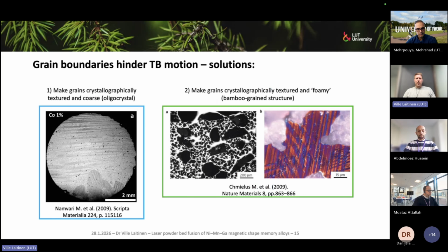Now, how do we get this to actuate if it is polycrystalline? There are a couple of approaches we can take. The foremost approach that is usually used is to make the grains crystallographically textured and coarse, so we make something like an oligocrystal, for example like this Co sample in the image here. We can have compositional additions to the material which induce grain growth, for example during heat treatment, or we can use certain processing steps to induce grain growth.